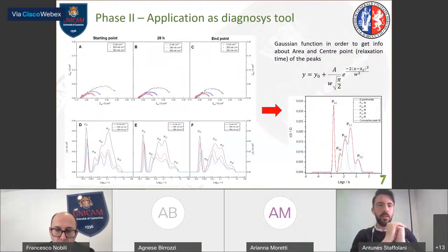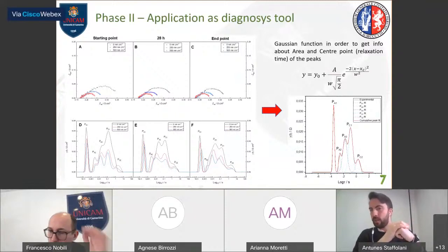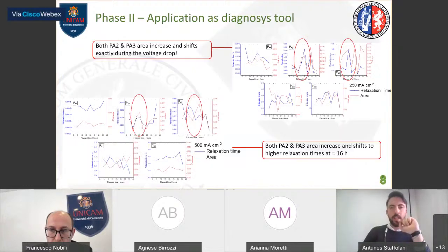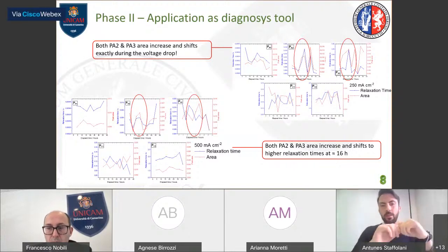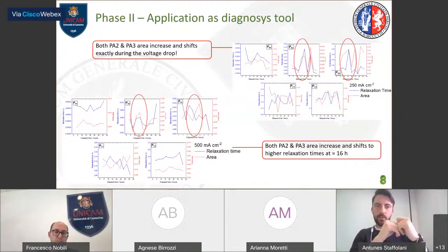And in order to have a better view of what was occurring inside the cell, we fit all the DRT peaks with a Gaussian function in order to have information about the area of each peak and the center point, which is the relaxation time. And we plot this information versus the stress time. And we have seen that 2 peaks, PA2 and PA3, related to the anode, the hydrogen oxidation reaction and hydrogen gas diffusion, suddenly change exactly at 16 hours. The area increases and they shift to higher relaxation time.